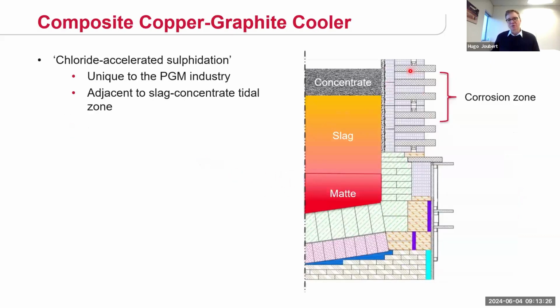So if we move up to the upper sidewall, of course, I think you are all familiar with this, the chloride accelerated sulfidation issue. It's quite unique to the PGM industry in South Africa. Basically, where you have your concentrate layer and your slag tidal zone, you have some sulfur coming off your concentrate layer, condenses on copper coolers in your sidewall, reacts with the copper, forms copper sulfide, which is the corrosion product. And that's how you wear it.